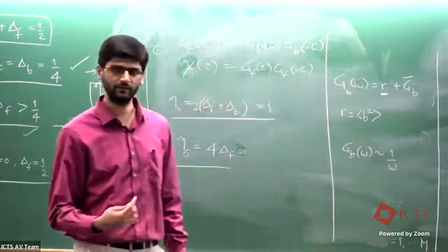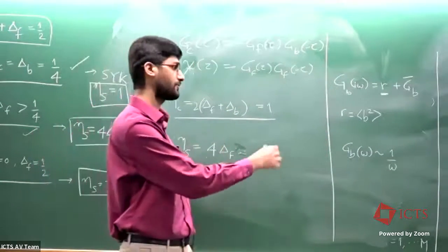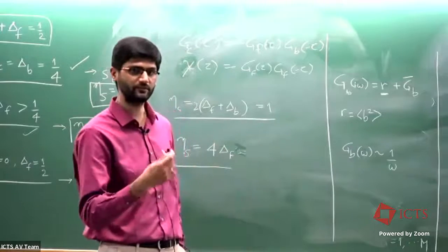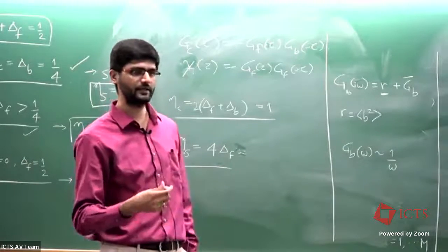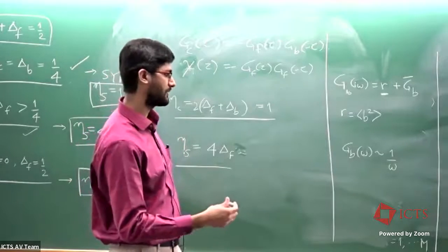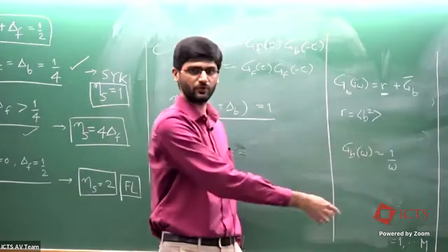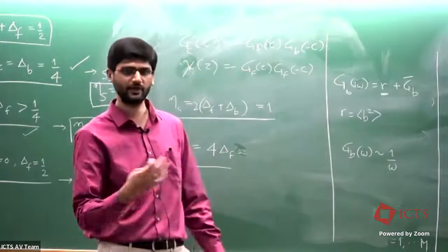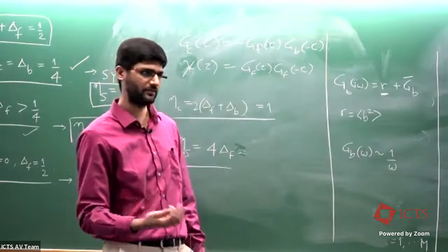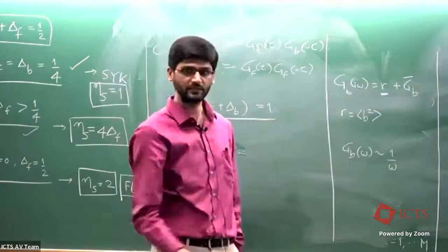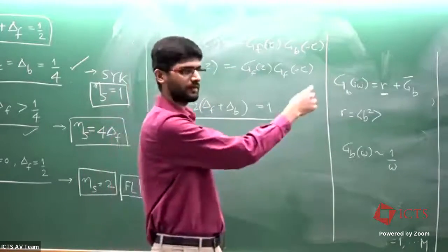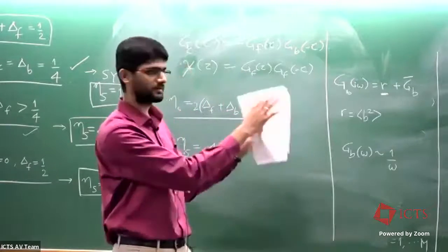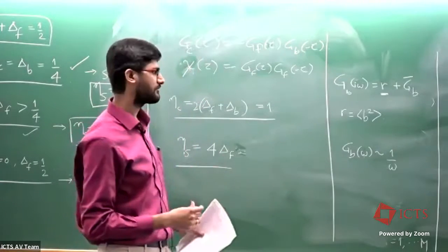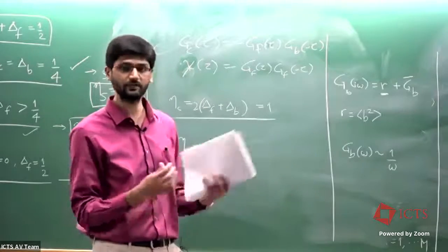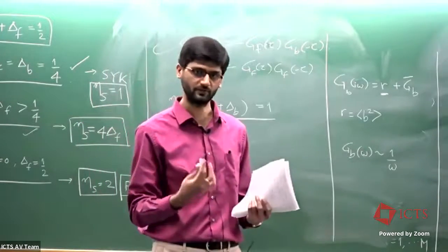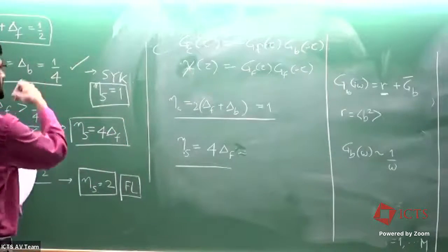And this is a problem because you have to solve all the equations, and you also have to satisfy all the constraints so that you get the correct value of doping and doping density, and so on. But if you have a form for GB which is 1/omega, you can immediately see that you get a log divergence when you calculate your boson density, because your boson density is like the integral of this GB of omega. That's the reason why, at least in this type of large M theory that I have been showing you, there is no Fermi-Liquid solution. So there are only two possible solutions, and these are both non-Fermi-Liquids.